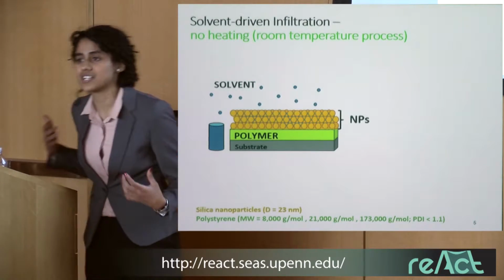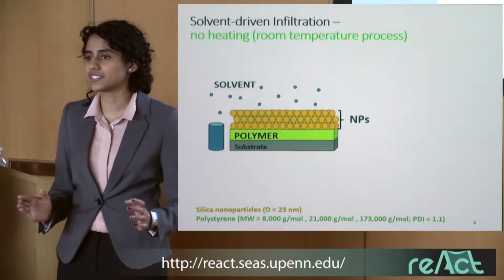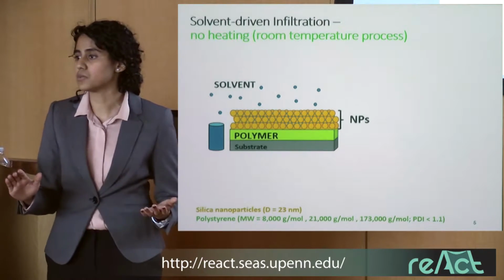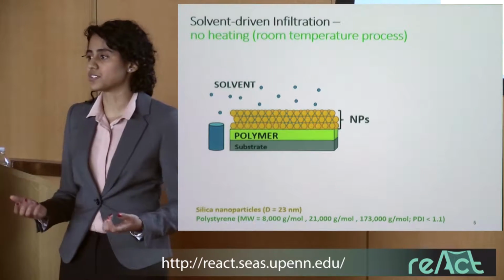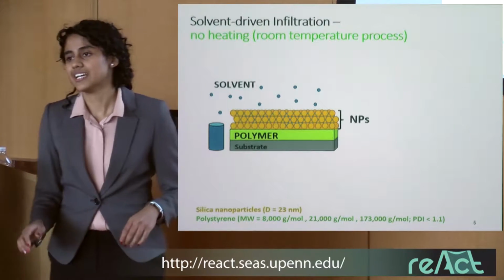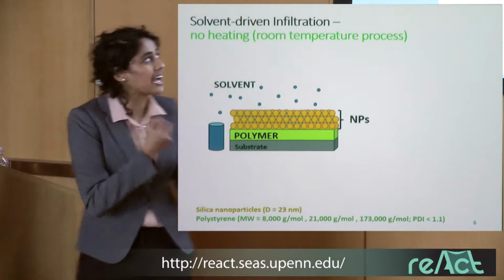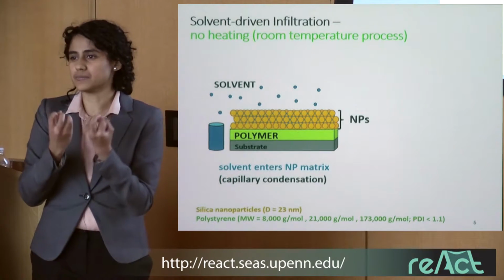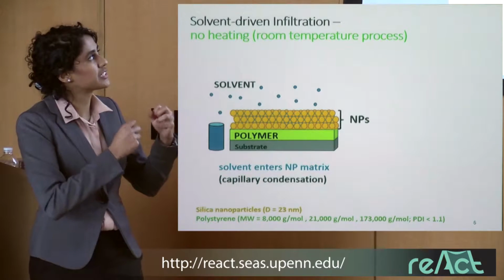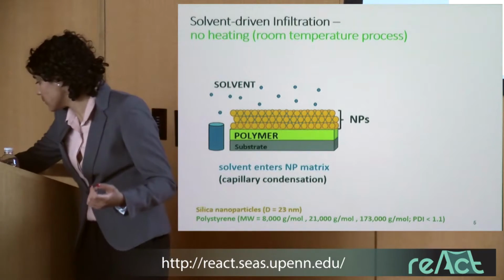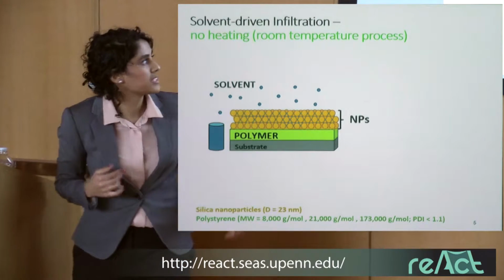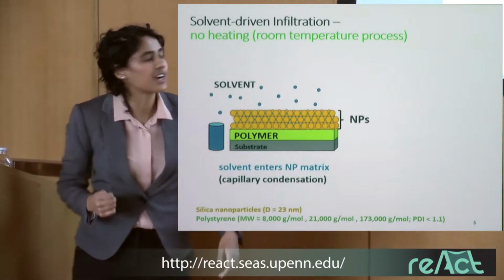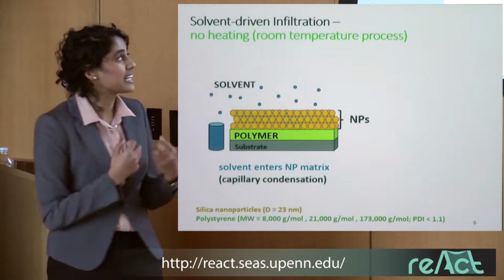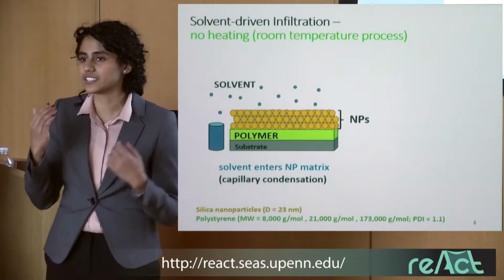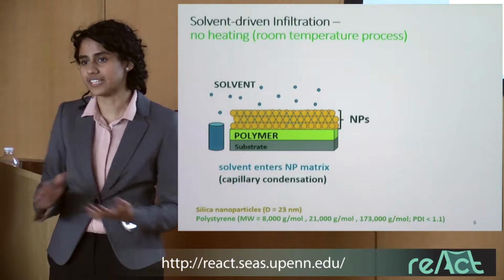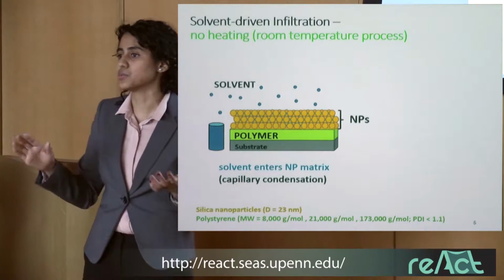So what my project entails, where I come in, is we have the same bilayer setup. We have these nanoparticles coated on a polymer film, and we expose it to solvent vapor. So we do solvent annealing instead of thermal annealing. And what happens when you expose this really high curvature, because these are 20 nanometer diameter nanoparticles, when you introduce this really high curvature environment to the solvent vapor, they want to condense by this phenomenon called capillary condensation. So basically the high negative curvature of the fluid interface leads to this stabilized liquid condensate phase that makes the nanoparticle layer flood with liquid solvent.